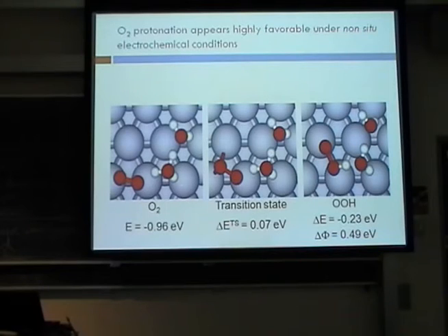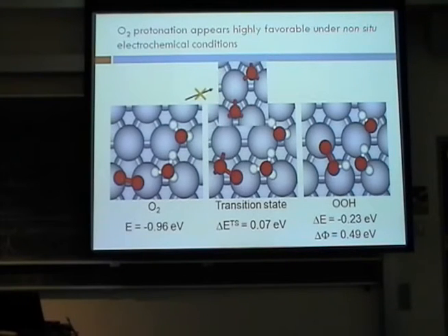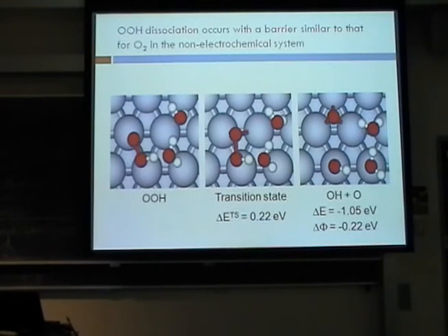the Damjanovic pathway that I showed earlier is the one that is energetically preferred. So that you undergo a proton transfer, a shuttling of the proton to form a peroxy intermediate when you have lots of water around. And that's favored over sequentially adding adsorbed atomic H, that they would rather add as a proton through this kind of very conventional proton shuttling mechanism. And you don't get direct dissociation of oxygen. That's disfavored actually by the hydrogen bonding network that's set up.